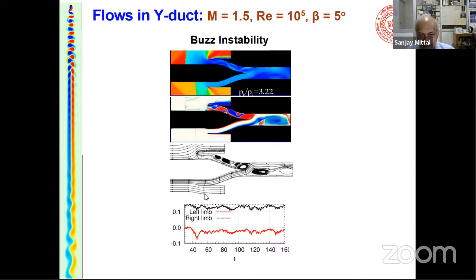And as you will notice, flow comes in through the lower limb, and in fact, it curls around and leaves through the outer limb. So in fact, one of the limbs shows a negative mass flow rate, while the other one shows a positive mass flow rate, and you get very little flow through the air intake. And this is not recommended for a real operation, but as a design engineer, you would like to know how the intake behaves so that you can avoid these uncertainties even in the testing phase.